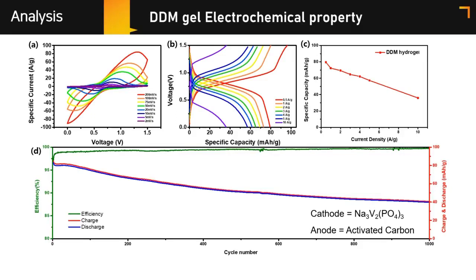NVP's theoretical capacity is 118 milliampere hour per gram, and the full cell's specific capacity is almost 80 milliampere hour per gram at the first cycle. In graph C, the DDM hydrogel battery has good rate performance until 5 ampere per gram. Graph D is cycle and charge-discharge capacity data. As shown in graph D, cycle stability is not stable due to the problem of vanadium dissolving in NVP. A suitable cathode for sodium-ion battery aqueous systems does not exist yet, and it is the biggest obstacle to aqueous sodium cells.